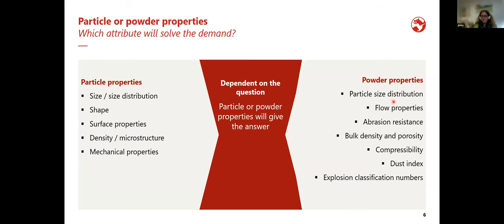For size distribution evaluation in powders, sometimes it's the distribution that matters — is it broad or very narrow? Do we have a lot of fine dust-sized particles, or larger particles indicating something went wrong in the process, like unwanted agglomeration? Bulk density and porosity are important as they determine, at a minimum, your packaging. The dust index is important for contamination within the production plant and has a big influence on explosion classification numbers, which are increasingly important in the powder industry.